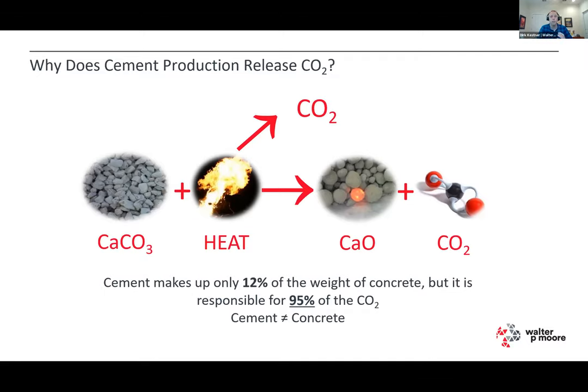The process of taking limestone — CaCO3 — adding heat, which emits CO2 just from the kiln energy getting it to thousands of degrees, produces the CaO. Just from the chemistry, you break out CO2. If you want CaO, which is the clinker, out of CaCO3, you're left with CO2. That's why, as a rough rule of thumb, every pound of cement emits a pound of CO2. The actual number is a bit lower, but for rough rules of thumb you can think of it as pound for pound.